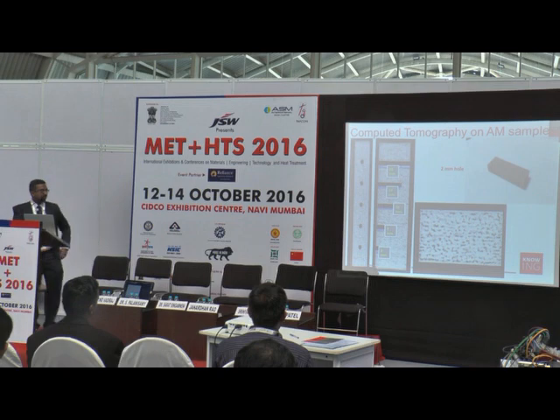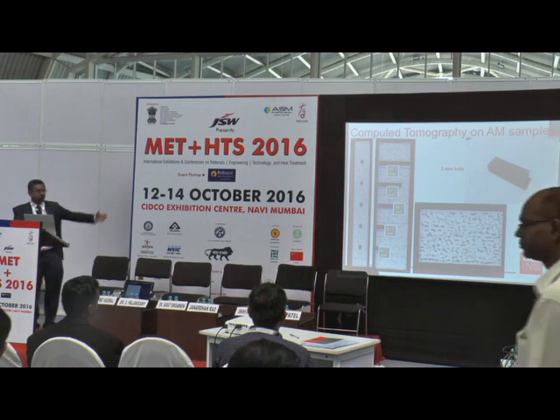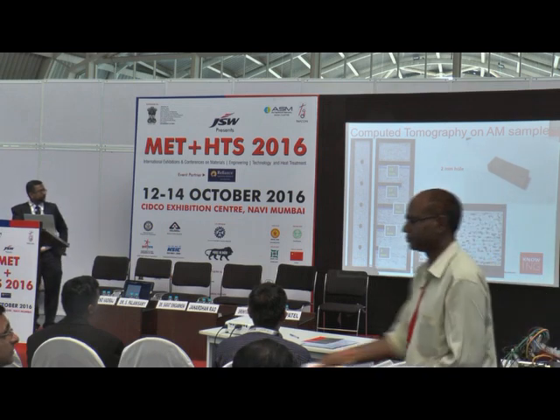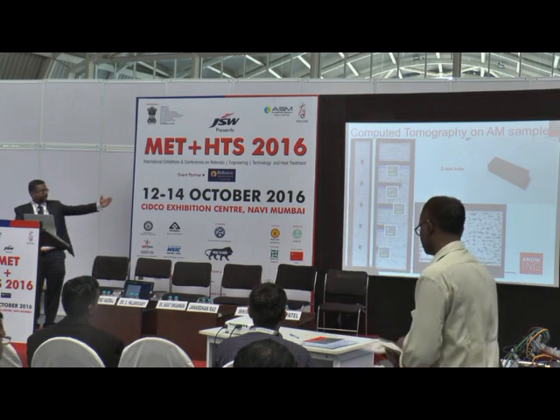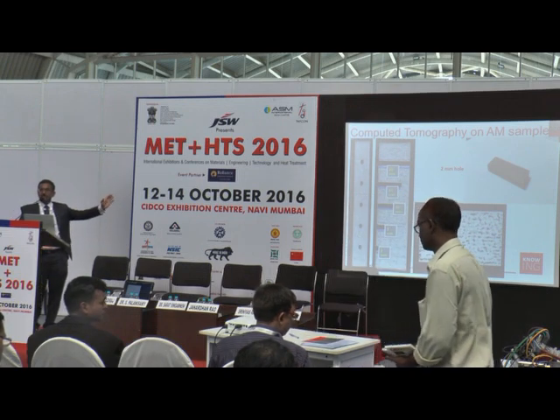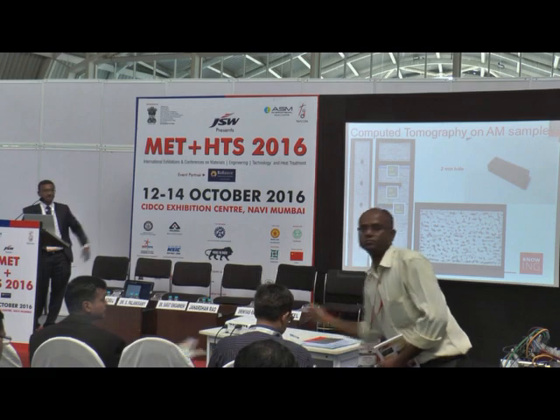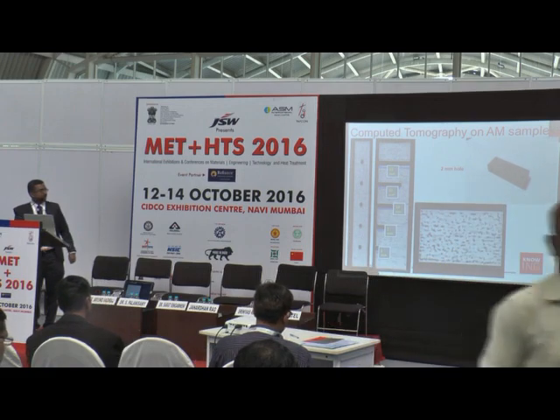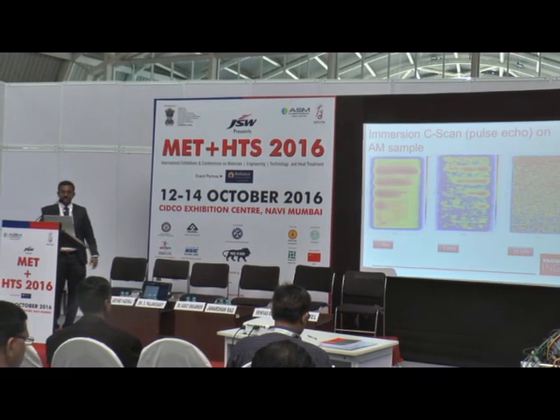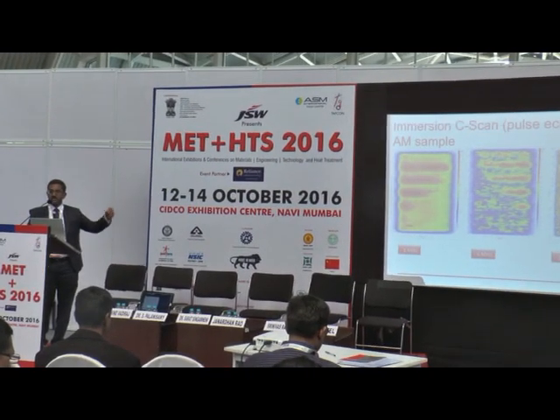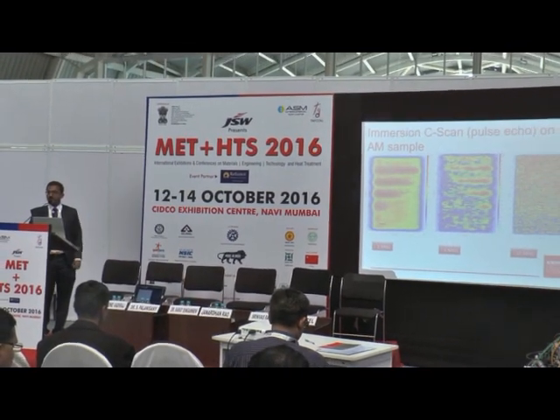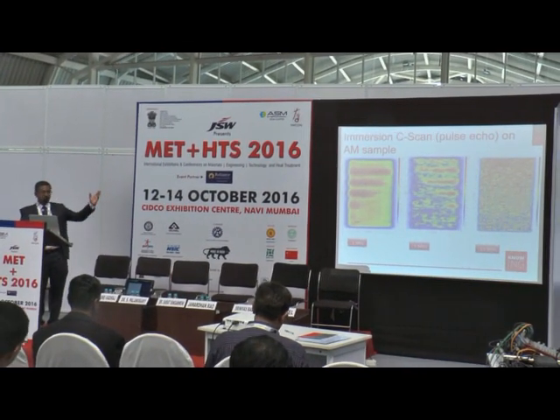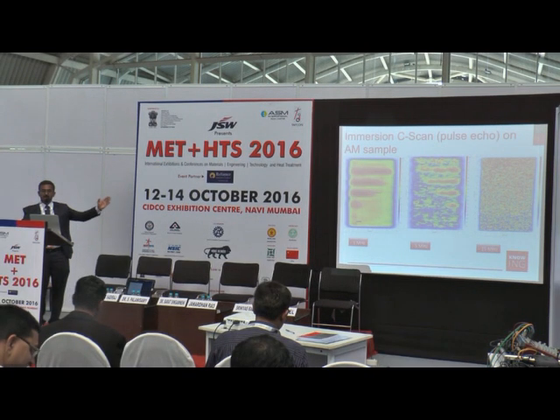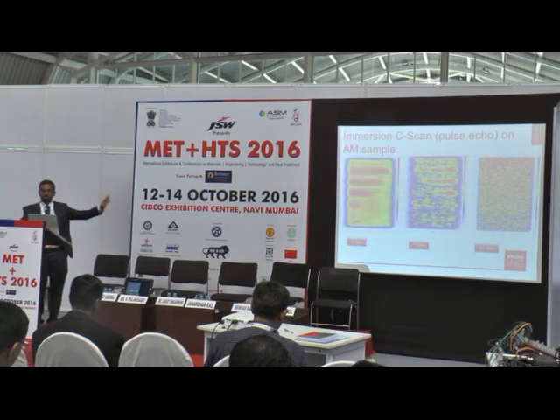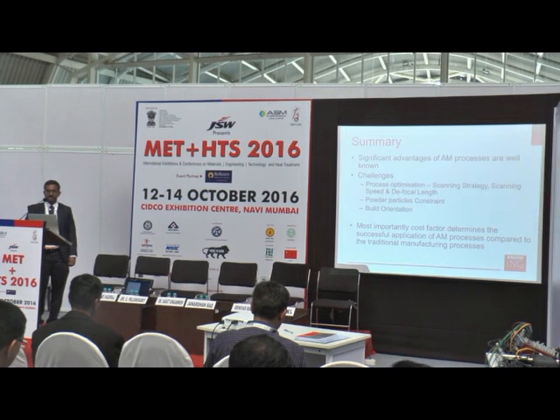So these are some examples we have done work on with IIT Madras, Chennai. This is the tomography work on additive manufacturing samples. As you can see, obviously we didn't optimize the process. You can see a lot of porosities there. These are two small simulated holes of 2 millimeters. And the same thing was done with immersion C-scan. Again, the challenge is the porosity. You can see that with different frequencies the intensity is varying, so you lose a lot of signal with the porosity.